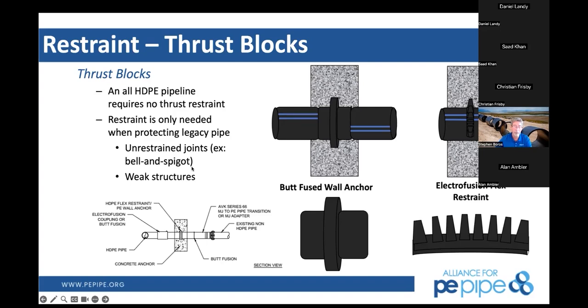But if you want to make sure that your bell and spigot pipes don't pull apart, there's two ways to mitigate that. You can put a thrust block in on the polyethylene and mitigate any movement there. But you should also probably put restrained couplings on those bell and spigot joints, usually 2 or 3 on each end, just to make sure that those don't pull apart either. So it's really not the polyethylene you're protecting, it's the old legacy systems you're protecting. But again, there are very common ways of doing that.